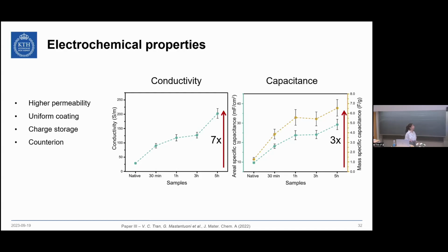We're also using the charge storage capability of lignin inside the material, which was not removed, and at the same time, the sulfonic groups are used as counterions and dopants for the polymer phase. There is a however, and it is that we've seen that the polymer was confined to the lumen space. However, if we want to make the most of the electroactivity of lignin, we need to access lignin better.